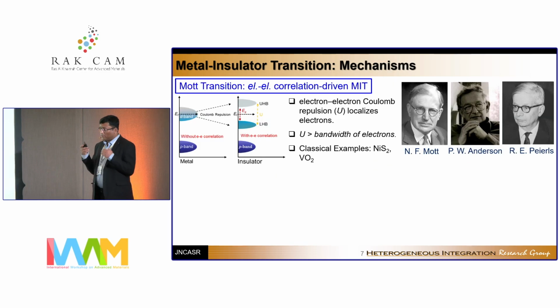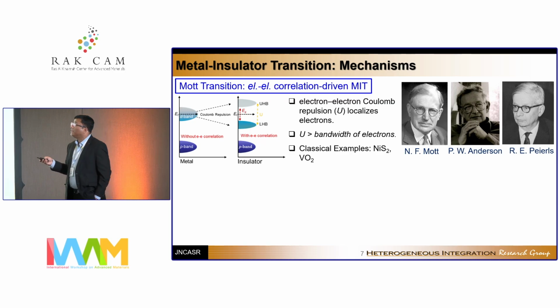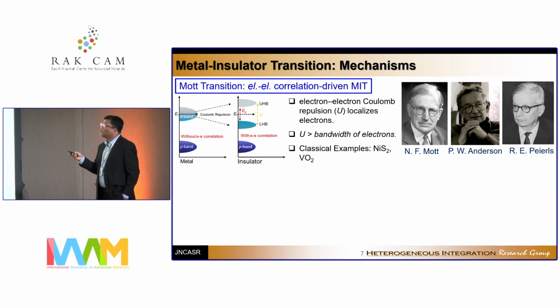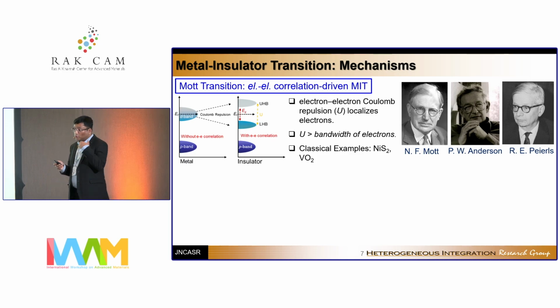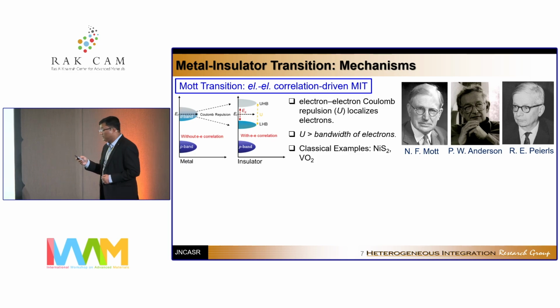Now, there are many mechanisms of metal-insulator transition that have been proposed in the last several decades, but I think none of them are complete without a specific mention of 3 mechanisms by Neville Mott, P.W. Anderson, and Peierls. In one case, the Mott transition is basically when the d bands of a transition metal near the Fermi energy split because of the electron-electron Coulomb repulsion, giving rise to an upper Hubbard band and a lower Hubbard band, and this causes an otherwise metal to act as an insulator.